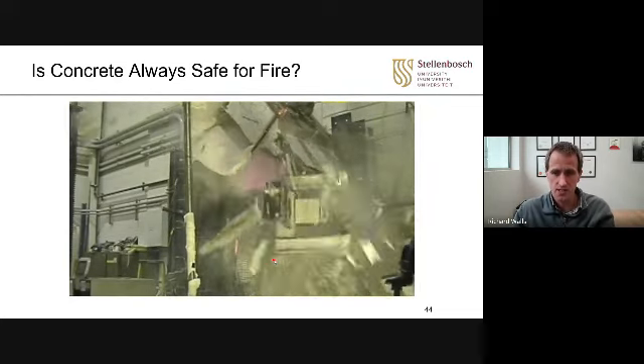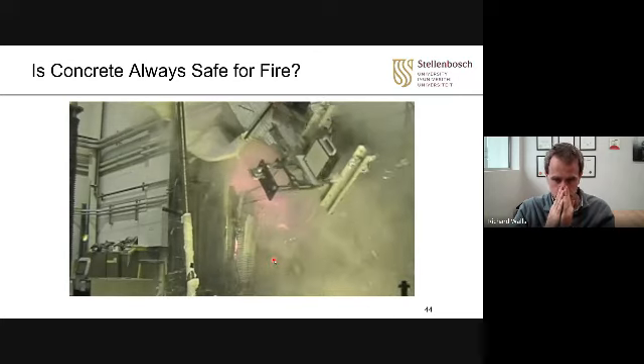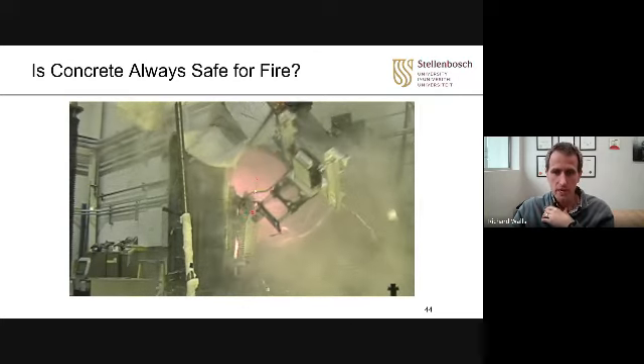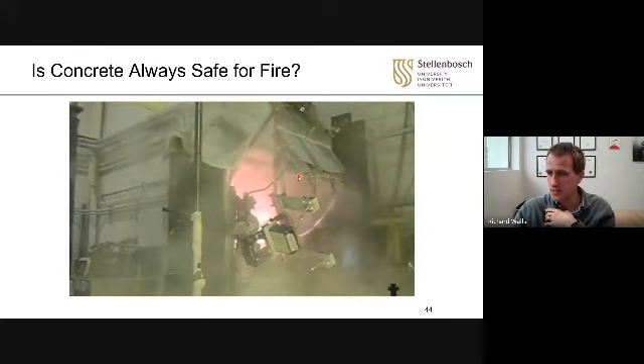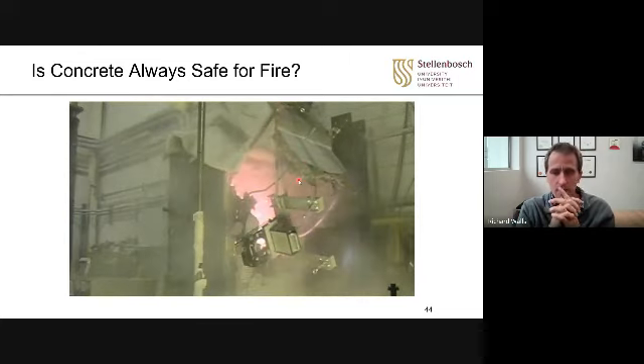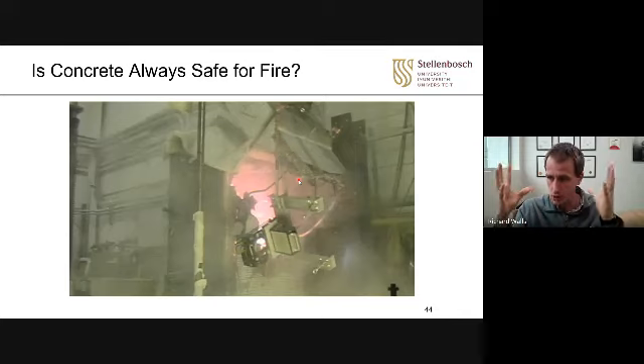So this was a test done at the University of Notre Dame. And here, the concrete was a high strength concrete, let's say 100 MPa or 150 MPa. Your dense concretes hold the moisture in because it can't escape. So when it heats up, your water converts into steam. Steam is much bigger than water, so it creates a pressure. Now it's pushing, and so it creates a pressure in the structural element until it blows. It actually bursts, and you'll have explosive spalling of your structural element due to the pressure buildup.